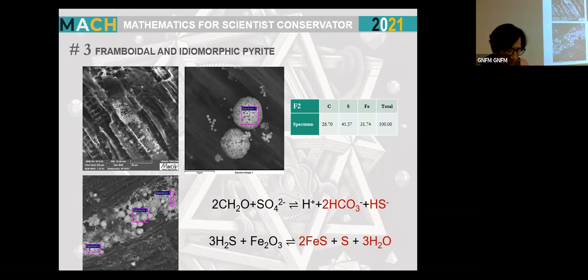The occurrence of both framboidal pyrite and weathered crystals reflects two distinct pathways of pyrite formation. Pyrite formed by bacterially mediated production of sulfide exhibits a framboidal morphology. Framboidal pyrite is the result of an early diagenetic reaction involving bacterial sulfate reduction associated with rapid iron reduction. During the sulfate reduction process, bacteria use the oxygen of freshwater or seawater sulfate to metabolize organic matter, resulting in the formation of carbonic acid and hydrogen sulfide ion. The dissolved sulfide reacts with iron-bearing minerals to form a stable monosulfide together with elemental sulfur.